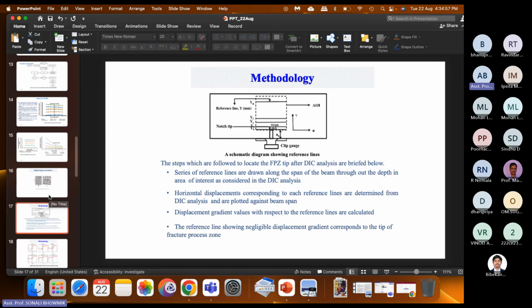So in that case, using those data, two methodologies were already developed. One methodology is to find out the fracture process zone size in terms of length. Another methodology is to find out the fracture process zone size in terms of width. Both dimensions are very important for the fracture process zone, because as I mentioned, this fracture process zone is crucial and totally related to the fracture behavior of concrete. If someone predicts the size of this nonlinear zone within the concrete, then one can understand how much energy the structure can absorb or dissipate, accordingly based on the problem. So here a method was already developed to find out the fracture process zone.